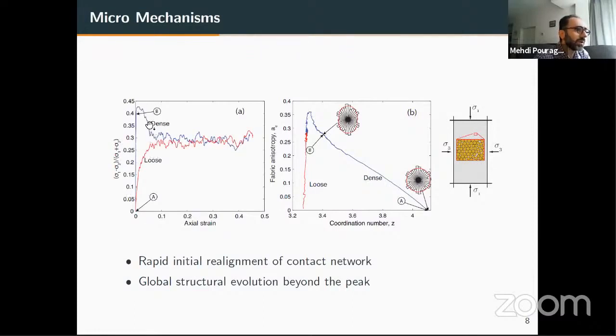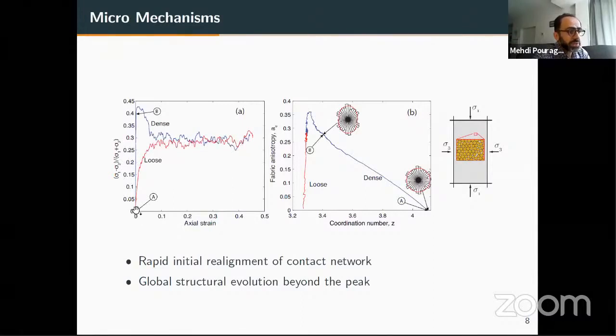So we're looking at typical dense and loose samples, and we see that for the loose, as we expected, the deviatoric stress, as defined here, is a ratio. It increases for the loose, and it reaches a steady state. But for the initially dense sample, for which the initial porosity is much smaller, we have a very rapid increase. You can see it's almost instantaneous. It goes up, it reaches the peak, and then it goes back down beyond the peak to the same steady state.